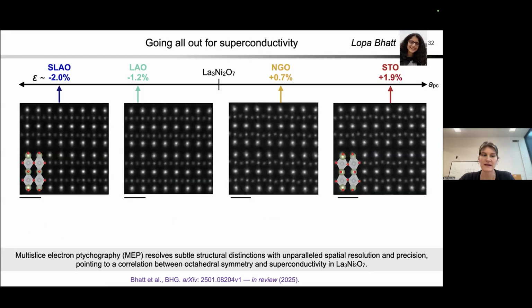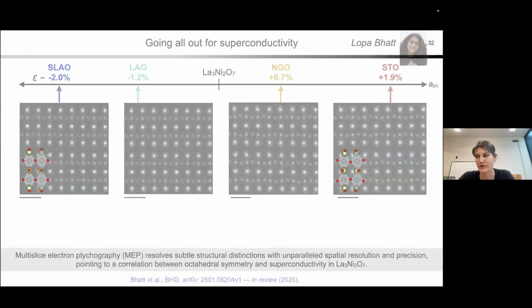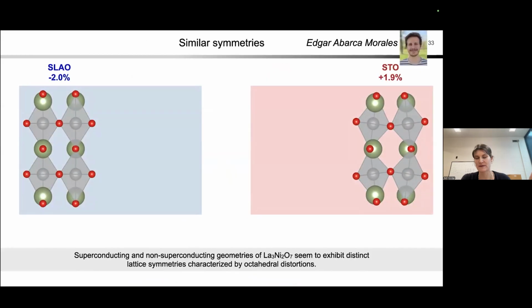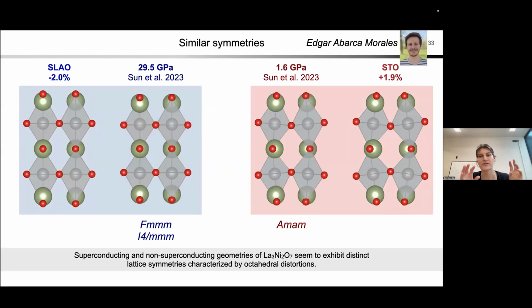And what's amazing is that we take these bond distortions and some of the other measurements that she can do, and we can turn these into basically atomic models for each of these thin films. If we compare those atomic models from the strained thin films with the atomic models from the original discovery paper of superconductivity in these samples, what we find is that our atomic model for the superconducting thin film is very, very similar and has basically exactly the same symmetry as the atomic model for the superconducting nickelates under high pressure, and that our tensile strain samples are very similar to the ambient conditions where there's no superconductivity.